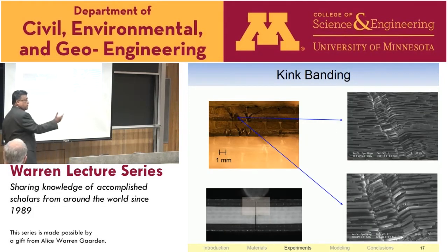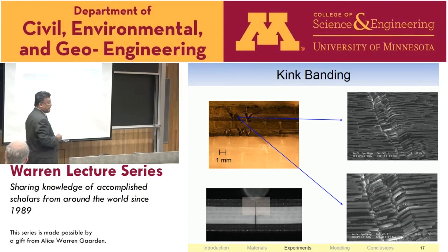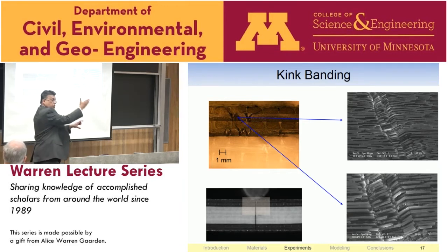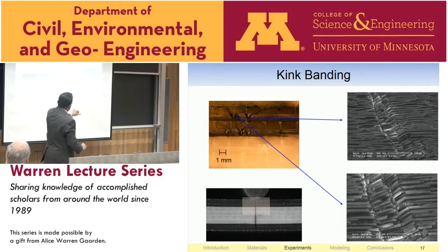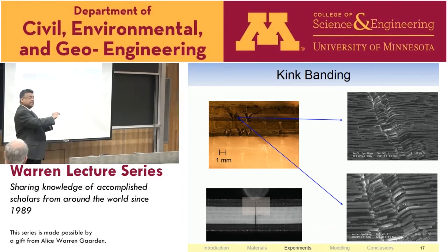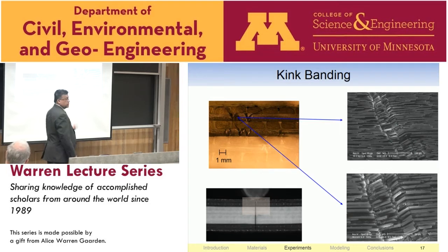The kink banding. There are some nice pictures in Professor Labuz's lab that I just toured, in the rock mechanics lab. Very similar. The fibers are straight, and then what happens is that you get a limit load instability, snap back, in the structural plane, but in the real structure, the unstable equilibrium path is lost. You get a vertical load drop, and you get a kink band, which is a band at a particular angle, right? And then at the corners of the band, the fibers actually break because the bending stress, the tensile stress on the fiber on the lateral side is much more, so it snaps. But that energy is small compared to the energy that is dissipated in the shear in the polymer matrix.